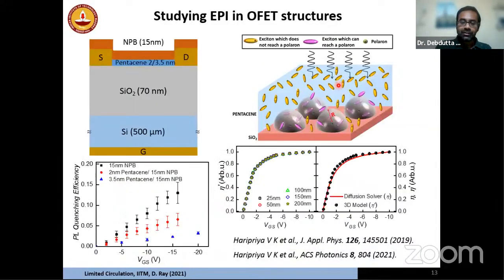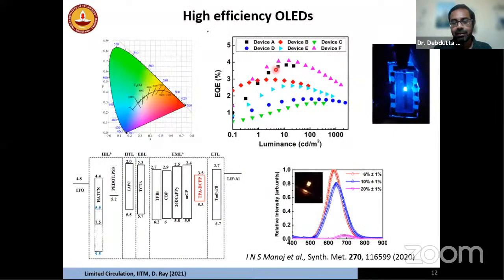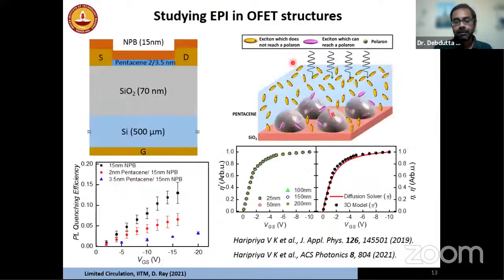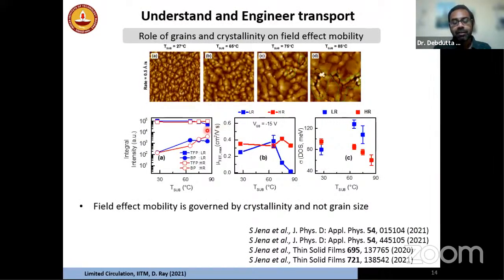So what we also need to do is study, again, I won't go too much into detail, how do these excitons actually quench? For example, we study how these excitons interact with carriers, which leads to quenching processes. If you have any questions on this, you can of course read our papers, and ask me later too. So basically what we try to do is decrease this quenching process between excitons and polarons, so that at the end of the day we have an EQE which looks like this, flat, so that at whatever intensity you drive your OLED, the efficiency should be the same.